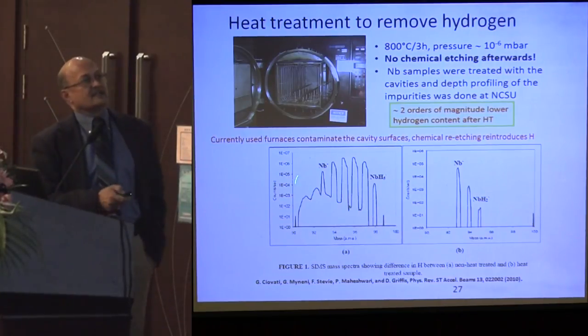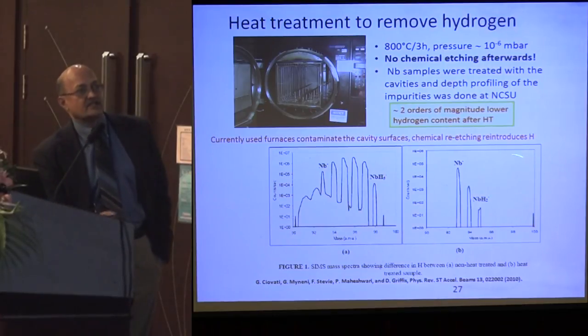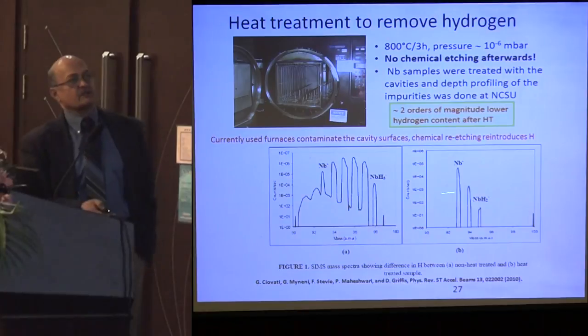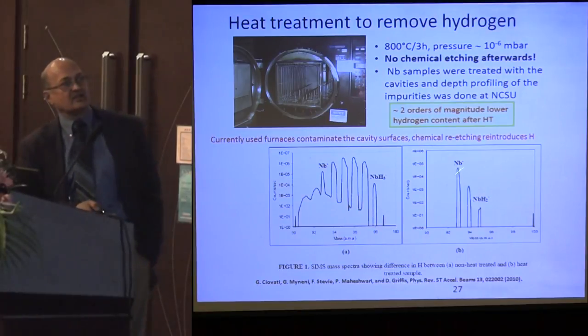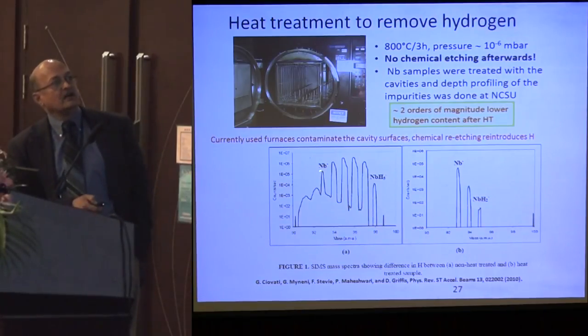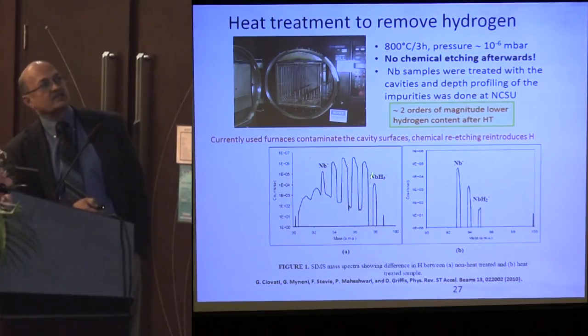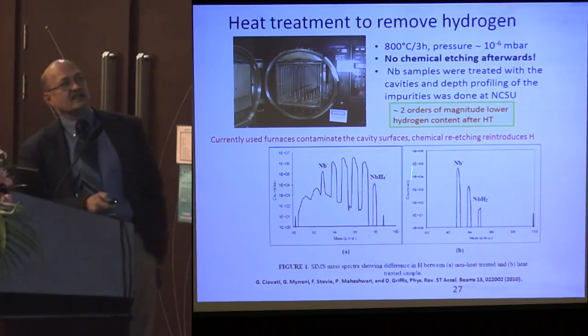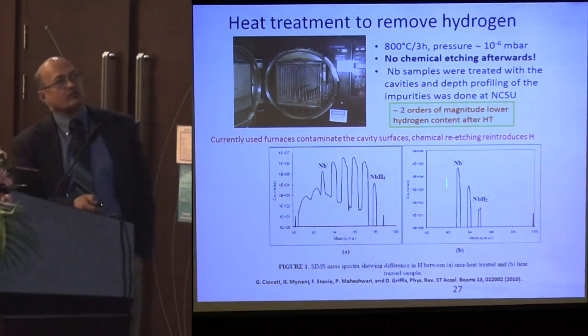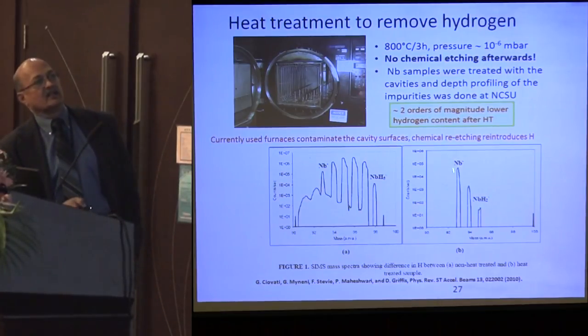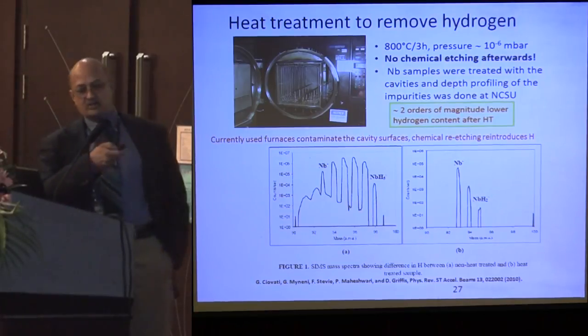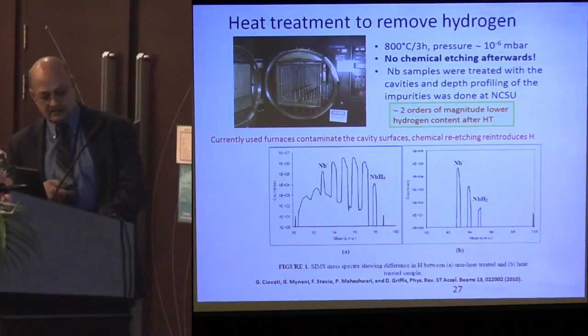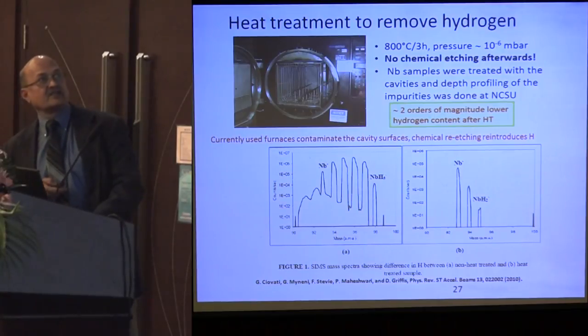If you analyze the samples, this is a non-heat-treated sample. This is the SIMS data, which shows you the hydrogen concentrations. Here you can see Nb, NbH, H1, H2, H3, H5. Whereas in the heat-treated case, you are removing a lot of hydrogen. You are only left with Nb, NbH and NbH2. So this actually plays an important role in the quality factor of these cavities.